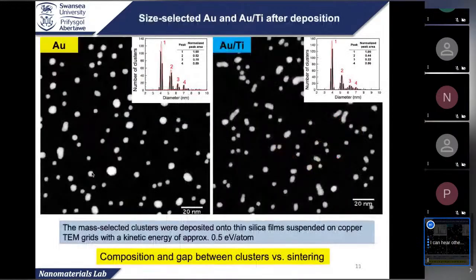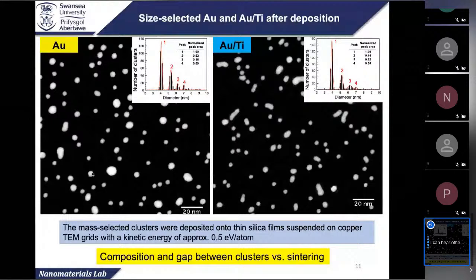So the idea here is we alloy the gold with titanium, and we studied the sintering process of those two kinds of materials. On the left is the STEM image of the pure gold nanoparticles, around 4 nanometer. It's size-selected gold nanoparticles, Au2057, which is a magic number as well. And then for gold titanium, we use a similar mass. You can see after deposition there's already sintering, which comes from the overlap of particles during deposition. Basically one particle located on the other one, then they become one particle during the deposition process. This is what we are not interested in, but it happens there.